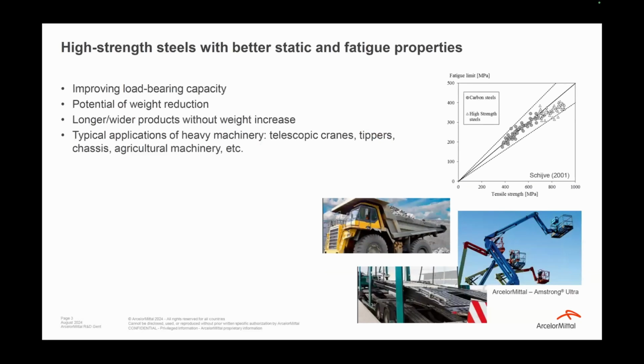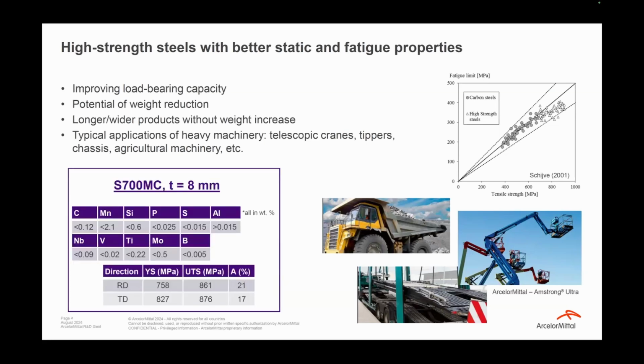So of course there's maybe a boring but a very logical reason why people want to use high strength steels, because they simply give you better static, not always linear, but still better fatigue properties. And of course, when you say high strength steels, you can think of different things. So what I am specifically talking about is what we call high strength low alloy steels. And the material that we used for this study is S700MC, which is a thermomechanical hot rolled grade that guarantees you over 700 megapascal of yield strength.